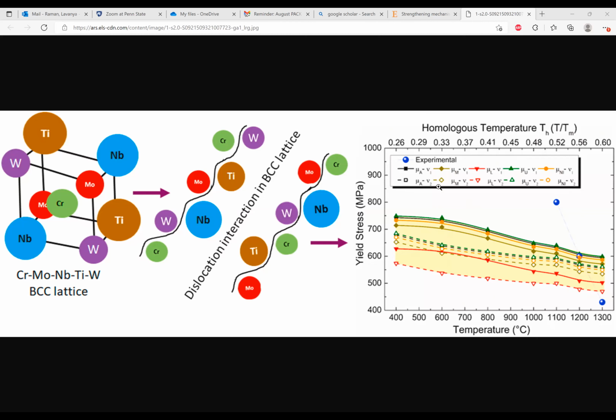What we did in our study was to use the shear modulus and the Poisson's ratio from different sources, basically from the established database or from the Materials Project. The Poisson's ratio we tried to estimate from the synchrotron studies. When we use different sources, we could see that the solid solution strengthening is very sensitive to these parameters. If you see this one, the mu-L from the Materials Project, when we take the lower value of the shear modulus, it shows that the yield strength is very low. But when we go with the values from the Ashby-Frost deformation handbook, it shows a very high yield strength.